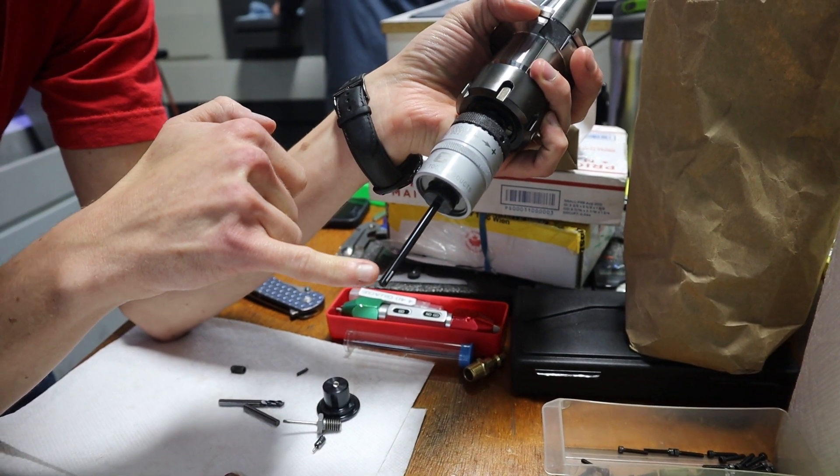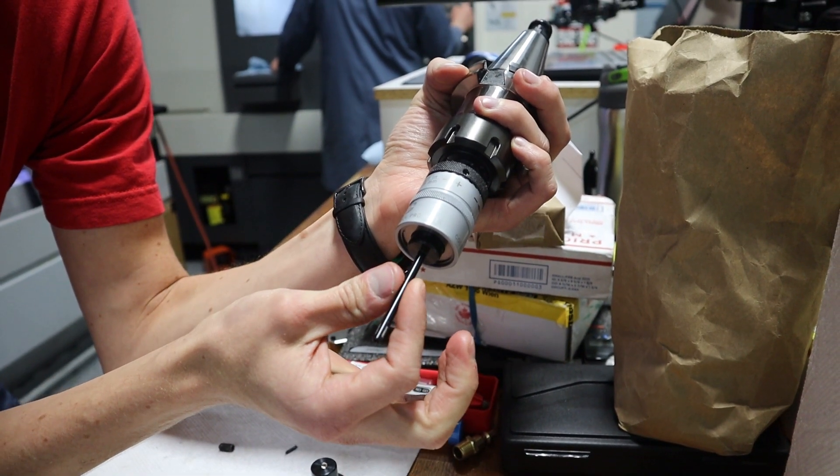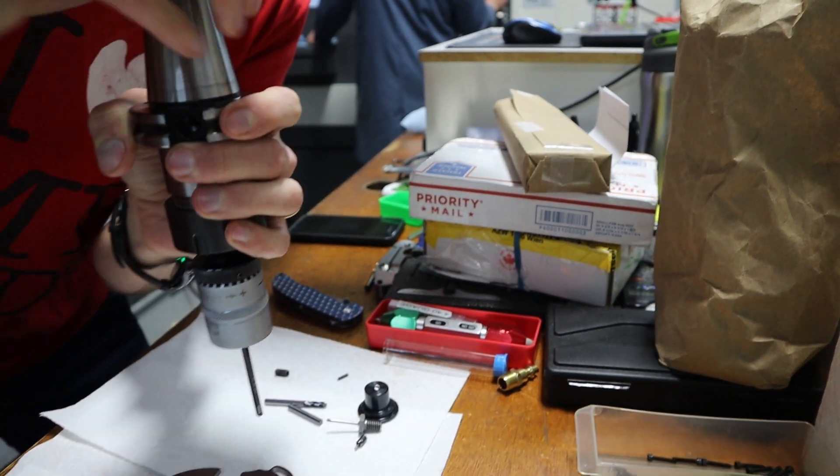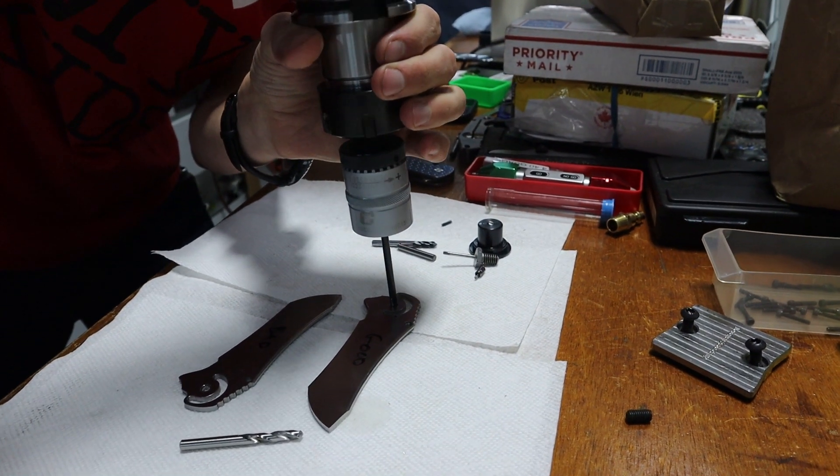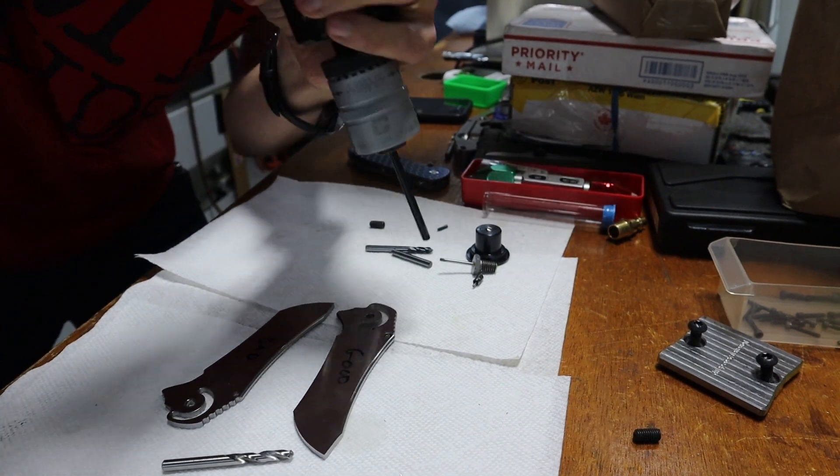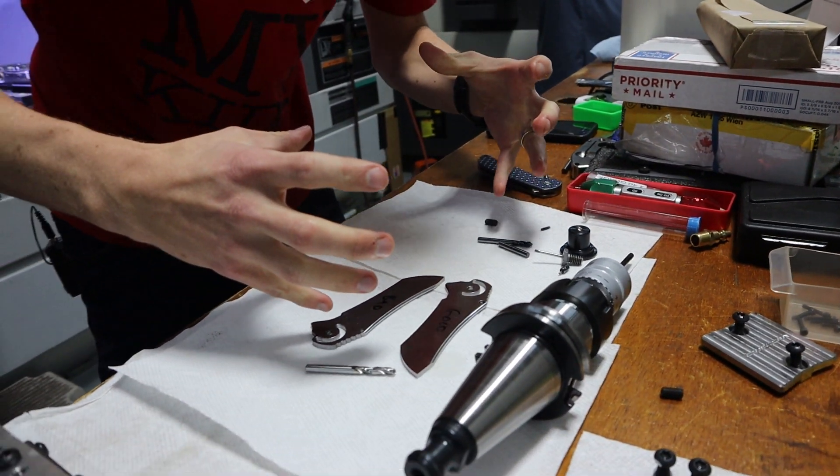It's super adjustable in one tenth increments as you put up the retainer and then rotate it. It's got a tapered mandrel here and three little tapered roller bearings. Basically you spin this thing, I don't know, 200 RPM, something really slow, into the blade. And then it burnishes the hole. Those little rollers roll around the hole and they squish all the material out.